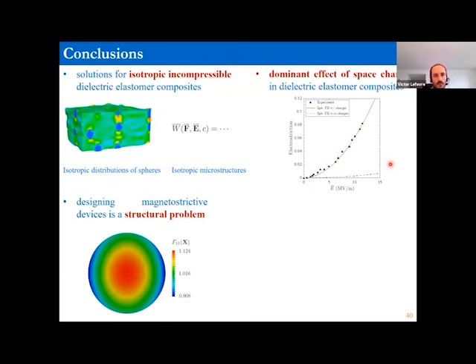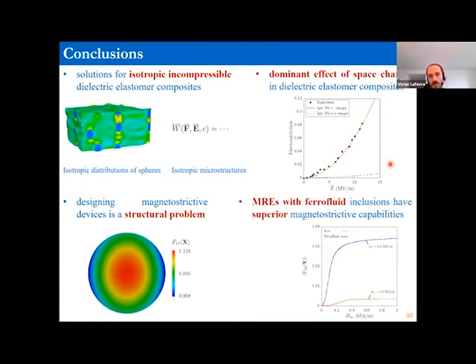And we showed that you will need to look at a structural problem when you're probing the response of this material experimentally. And we proposed that using ferrofluid inclusions instead of the stiff iron inclusions leads to MREs with superior magnetostrictive capabilities. Just want to conclude by mentioning two things, or one thing, I guess.